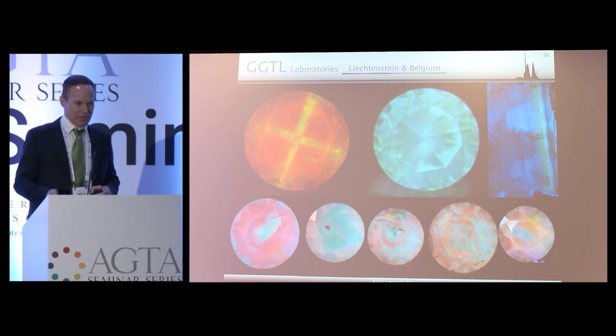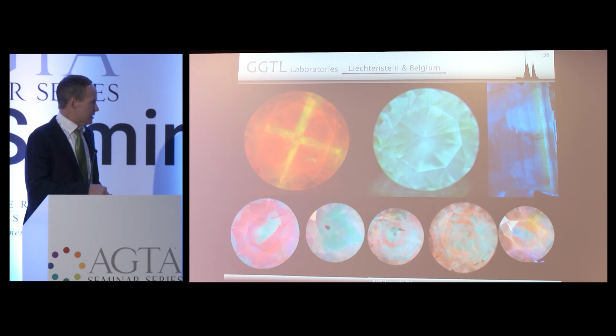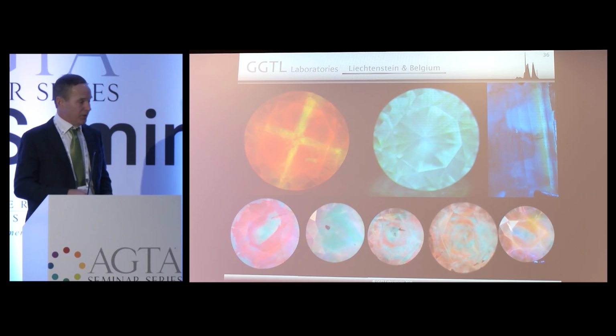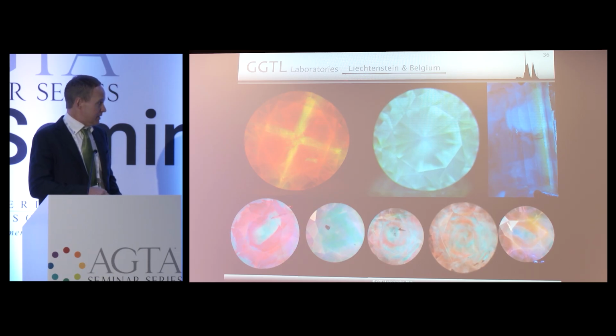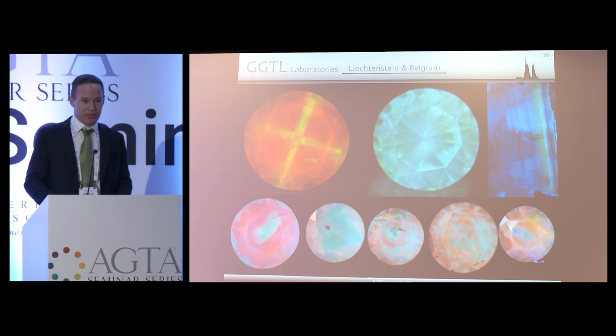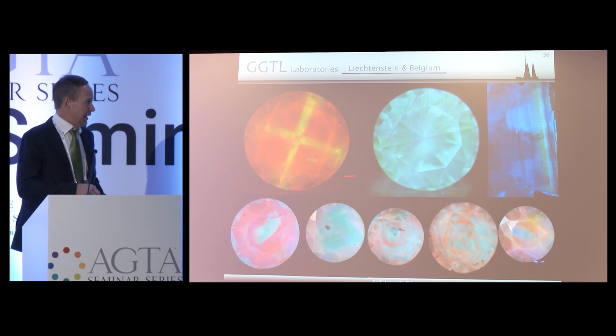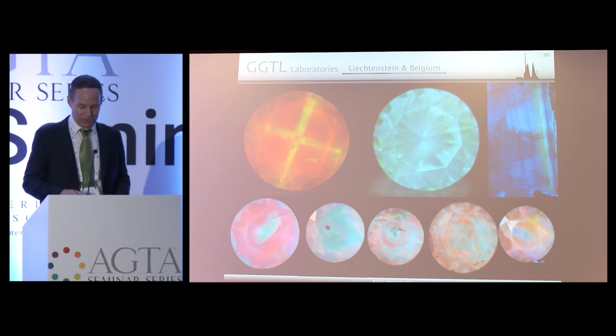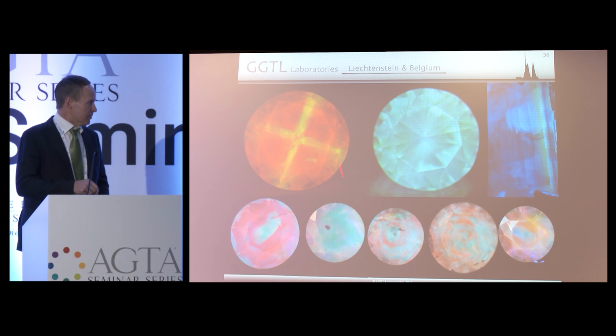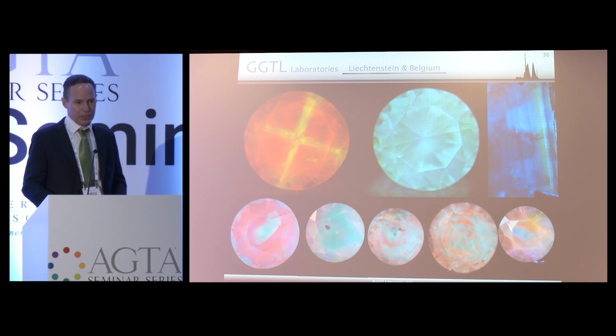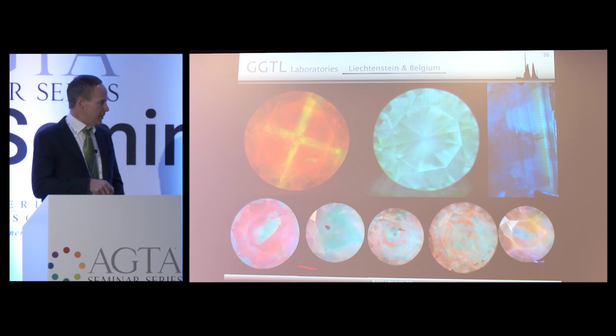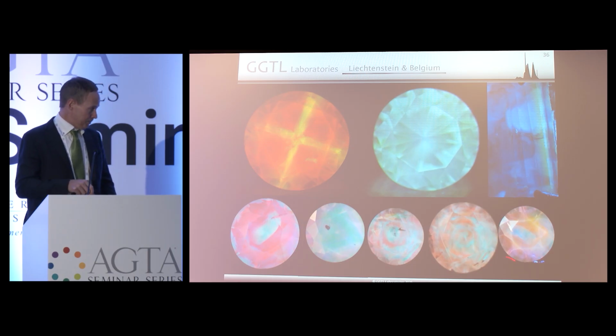If it's a type 2A and it fluoresces like that, if it's a type 1B and it fluoresces like that, if it's a type 1A and it fluoresces like this, you know the stone is either treated or synthetic. You can't tell from this without experience whether a stone is natural or not. But this is actually a natural diamond that has been irradiated and annealed to make it purple. These are multi-treated stones that have been HPHT treated, irradiated and annealed to make them pink to red.